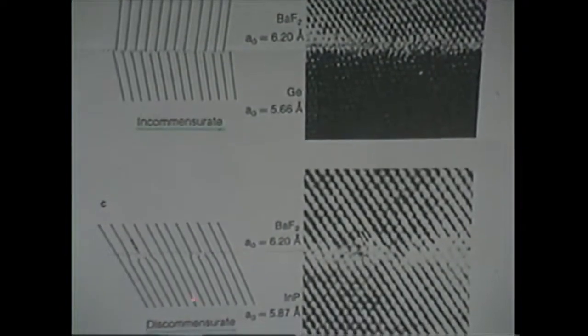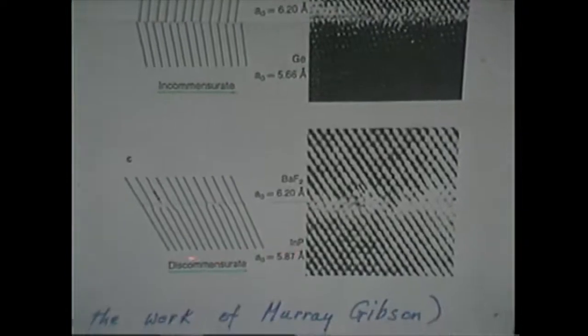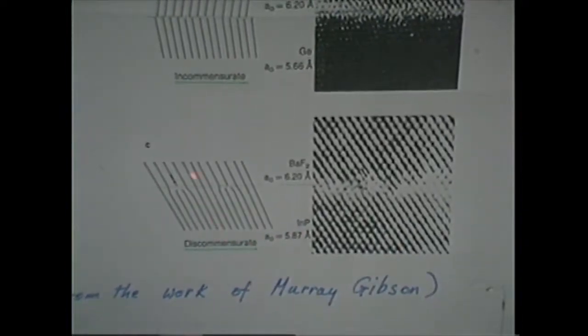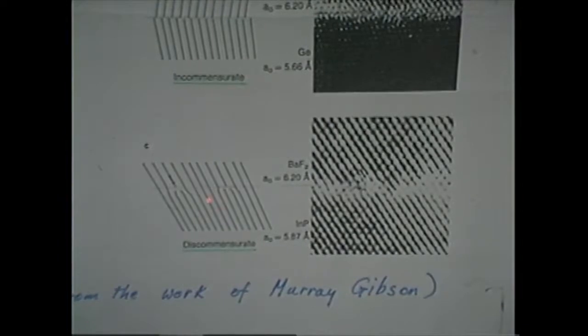However, for intermediate cases where the lattice constants don't differ by that much, you can form something that's called a discommensurate phase, where locally you get phase matching, you have good registry between the two materials, but because the lattice constant here is significantly smaller than the lattice constant up in here, you have to have extra planes. And the extra planes are what's called discommensurations. Now, sometimes these discommensurations form periodic structures all in themselves. And when that happens, it's called the stripe domain phase, and I'll say something about that.